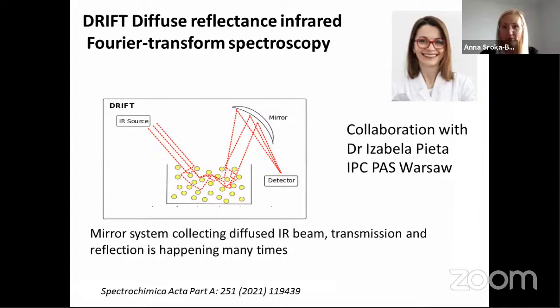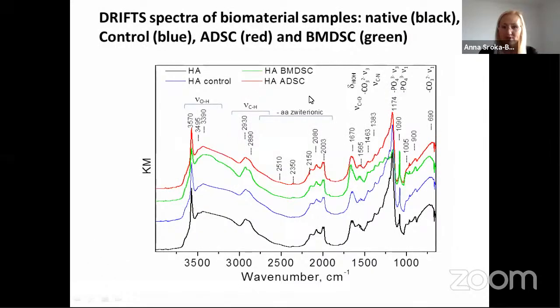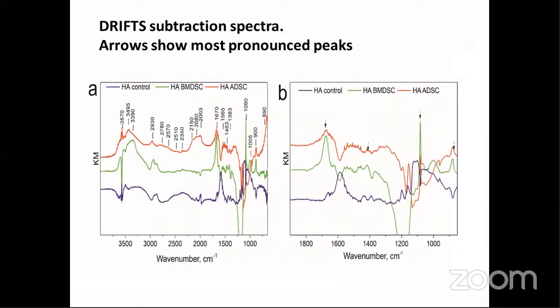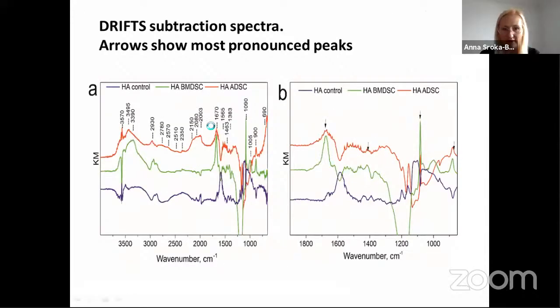The first part of the presentation was the contact with the crystal. The second part was the Raman imaging, and the third part is DRIFT. So it's a reflectance from the surface of the biomaterials. We use our four samples: the native, so the control, which was the pure biomaterial, and two samples which were incubated with the stem cells for 21 days. We noted the differences in those peaks and bands. This is the subtraction of those bands with this line, and we would like to see the difference in the lipids, carbohydrates and phosphates between the samples.